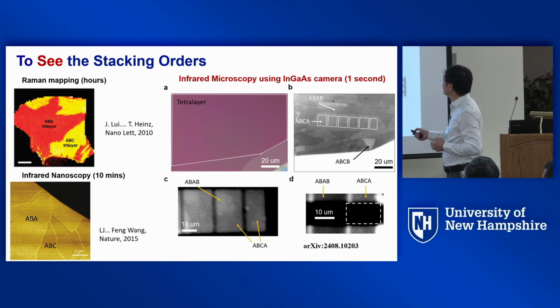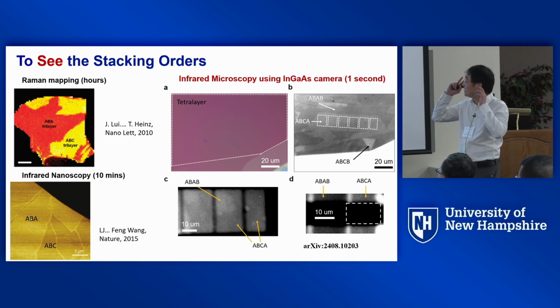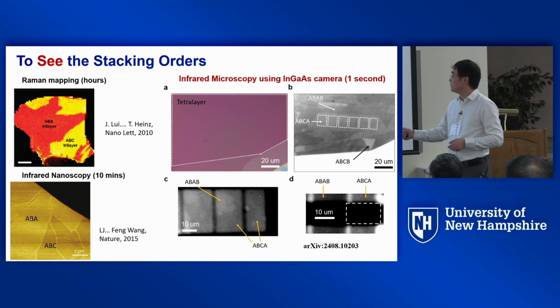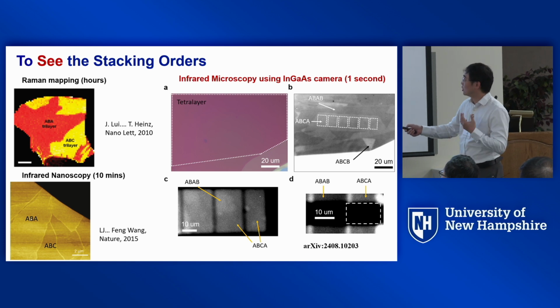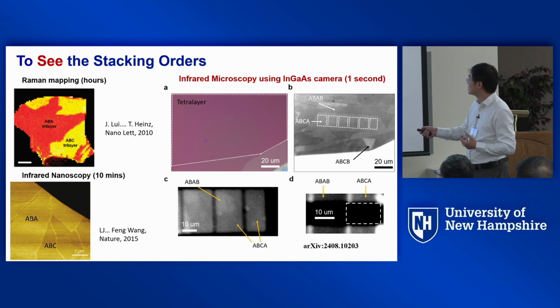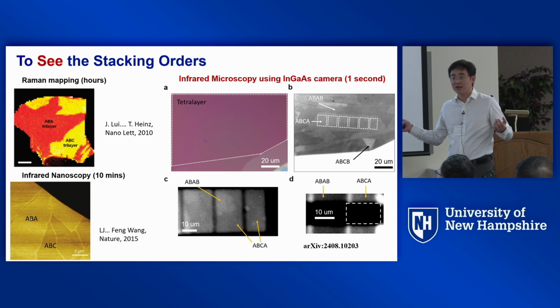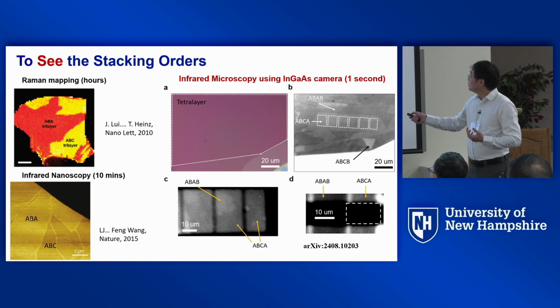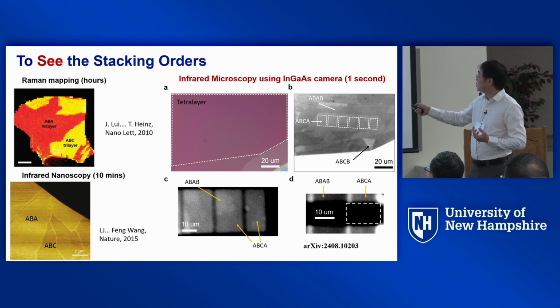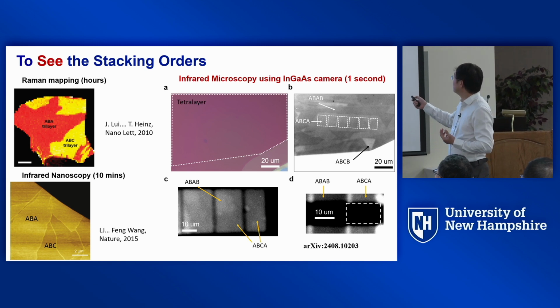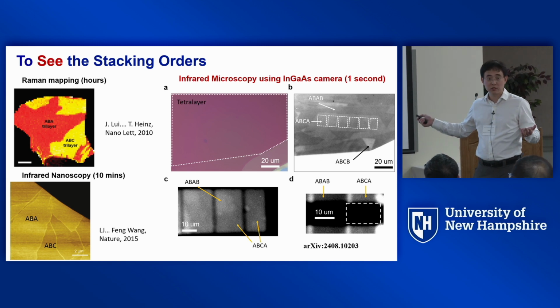Our most recent development in seeing stacking order, instead of indirectly determining the stacking order by using some spectroscopy, is to just use an infrared camera made out of InGaAs instead of silicon. You see, this flake is four-layer, tetralayer. It's homogeneous from the visible channel. But if you look with infrared light, within a second, you can tell where is AB, which is Bernal stacking, and where's ABCA, which is rhombohedral stacking.